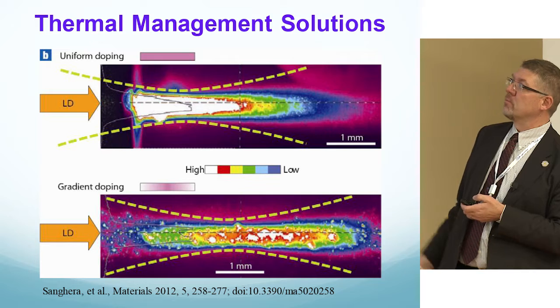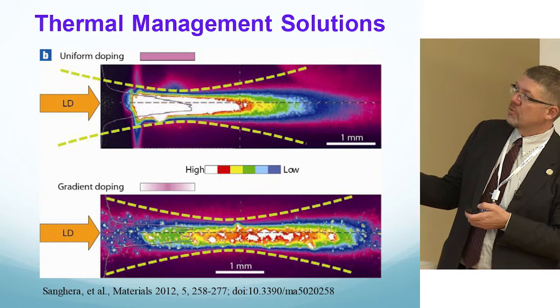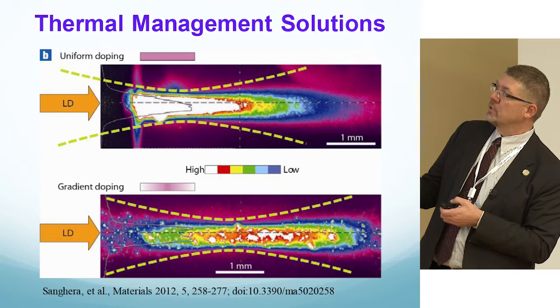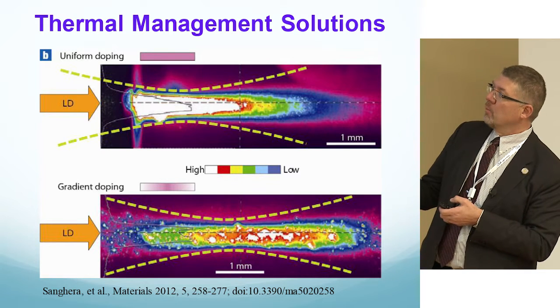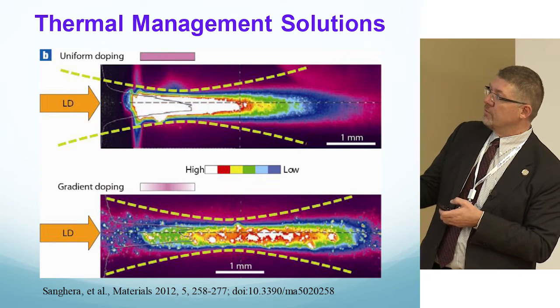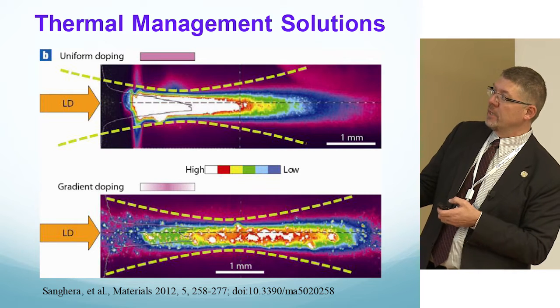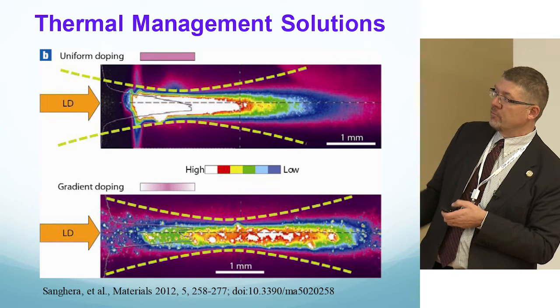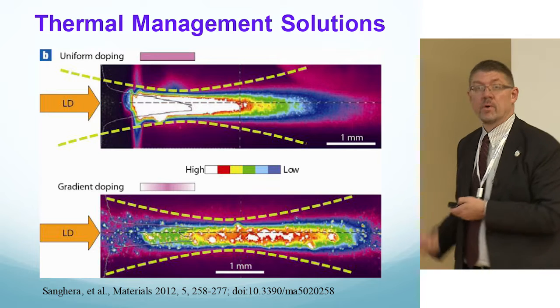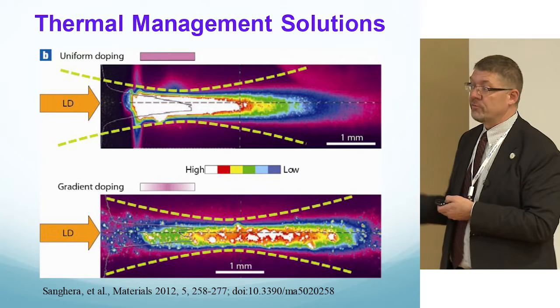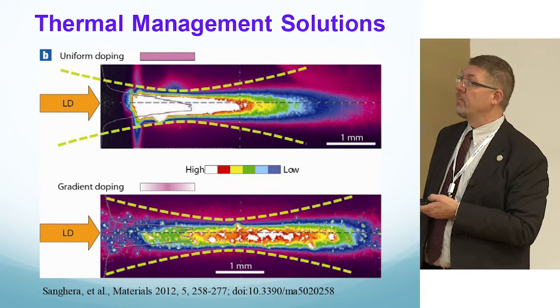They've also looked at thermal management. Look how high this thermal lensing starts taking place here. You just start to get a tremendous amount of distortion and very high blooming. When you change and go to the gradient doping, you see very, very little white in there, and definitely not any up here in the area where most of your pump beam is being absorbed. So there are ways to engineer these materials to be much more efficient and put out better beam quality.